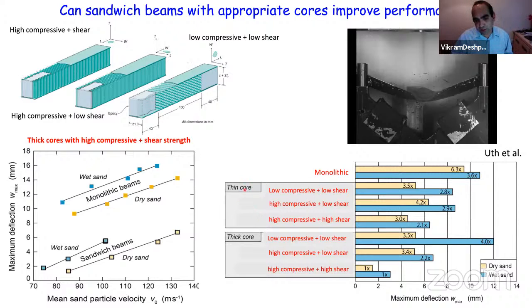Now, if you go to a thin core and a high compressive strength and high shear strength, how do I go to a thin core? You basically just halve the thickness of this core, but you make the face sheets thicker to keep the mass the same. Well, it's not doing as well as this one because this deflection is higher than in this case. So the lesson you're learning from these experiments is thick cores with high compressive strengths and high shear strengths